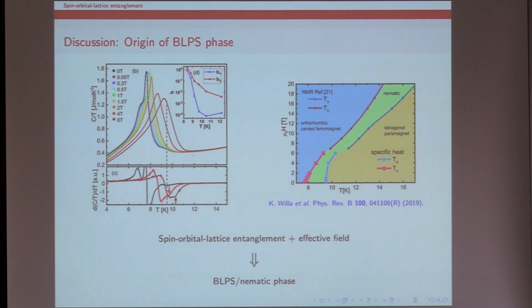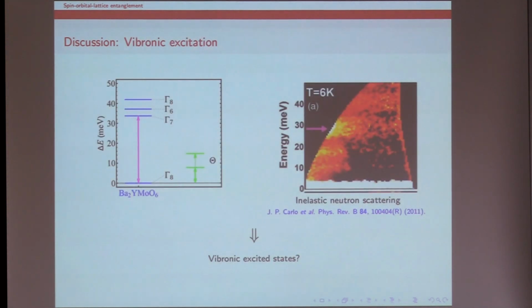This is a recent data of specific heat, and it is explained many times, and these authors discuss that because of spin orbital entanglement, their magnetic phase is influenced by effective field, and even without applying magnetic field, they obtain such a gap between paramagnetic and ferromagnetic phase. So this may support our idea. And finally, this is a molybdenum compound, and we obtain more or less similar spectra, and we expect in this system there is a dynamical Jahn-Teller effect also.